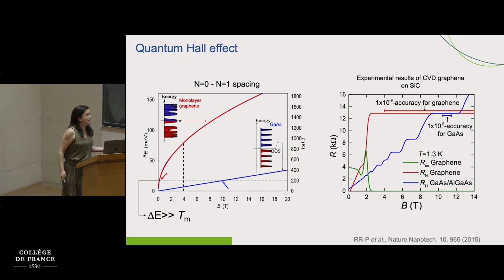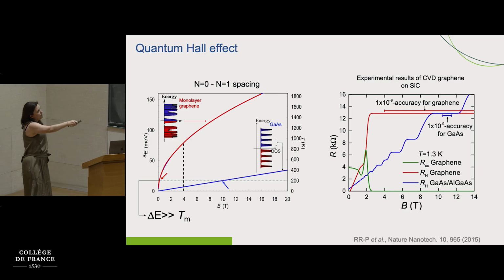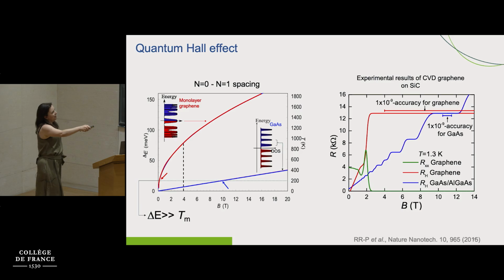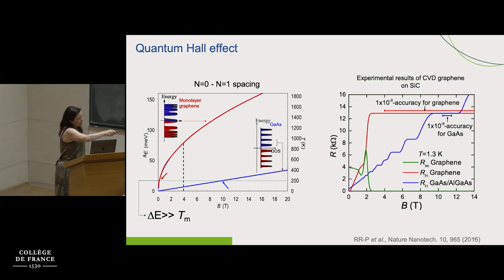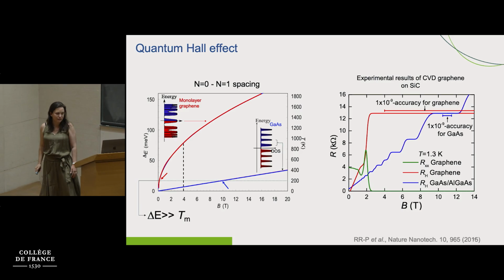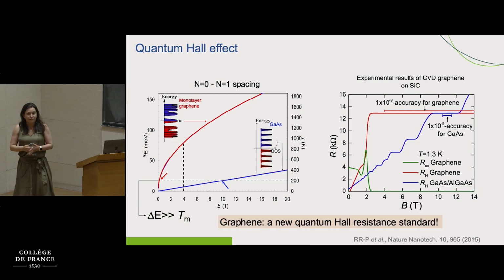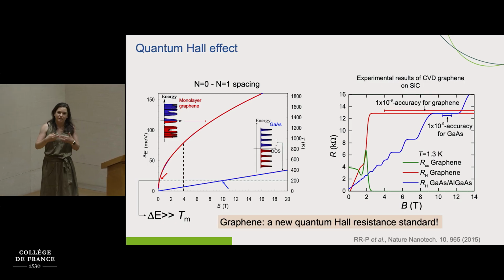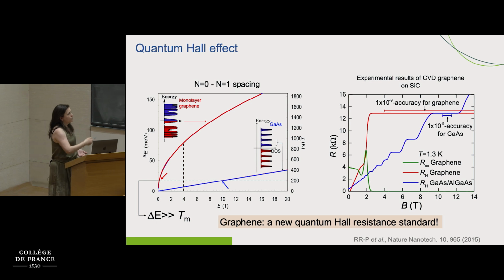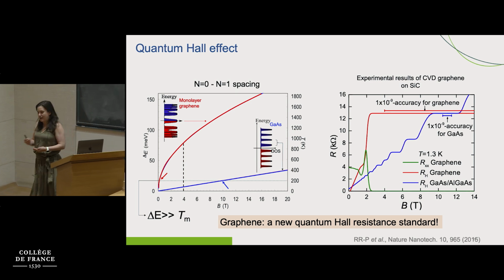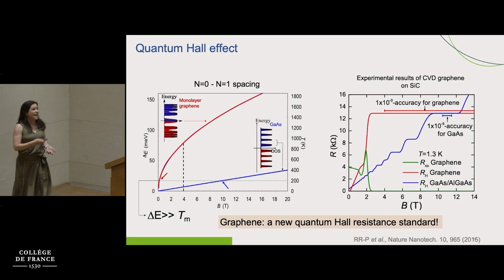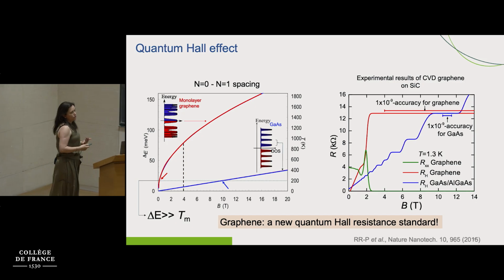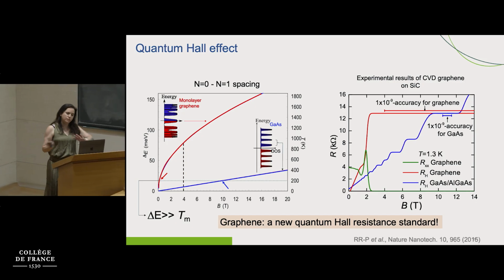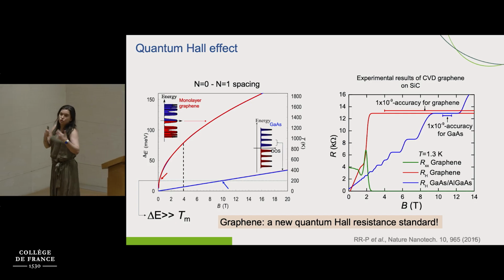In the case of graphene, on the contrary, we're going to be around 4 Tesla, and it's going to be accurately quantized all the way even to much higher magnetic field. So what this means is that graphene, even in its basic characteristic that is just Landau level formation, has already surpassed some materials such as gallium arsenide, and it's now used as the new quantum Hall resistance standard. But that's CVD graphene on silicon carbide. So this is not a super clean system.